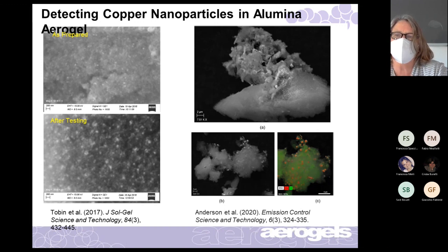And this is alumina, which is a little bit easier to take images of. So you can see we're in very close. This is 200 nanometer scale shown here. You can see some pores, but again, it's very hard to get enough information to get a distribution of pores. But we also see these bright spots here, which said to us, okay, those are pretty small nanoparticles, at least we think they are.